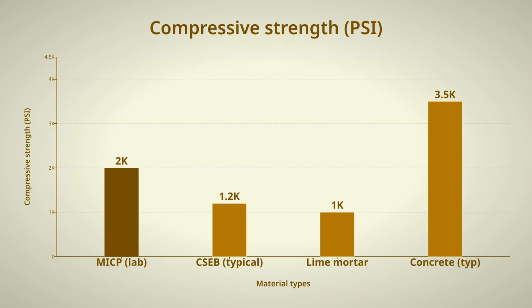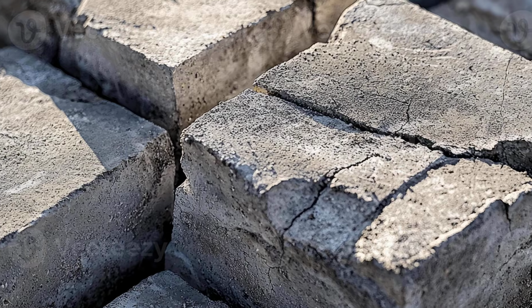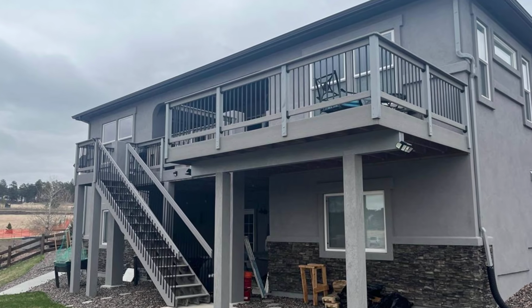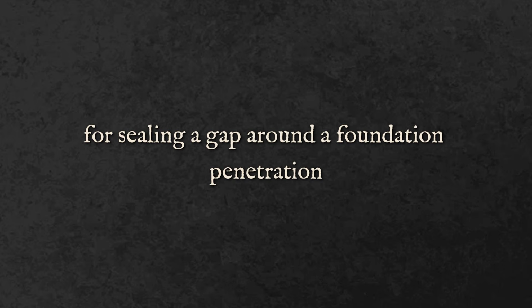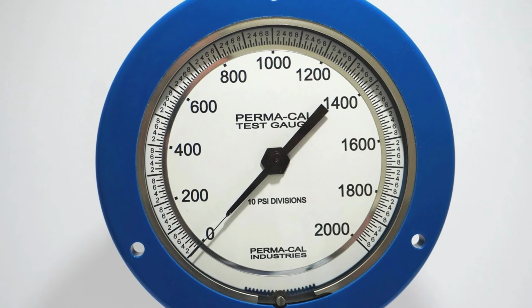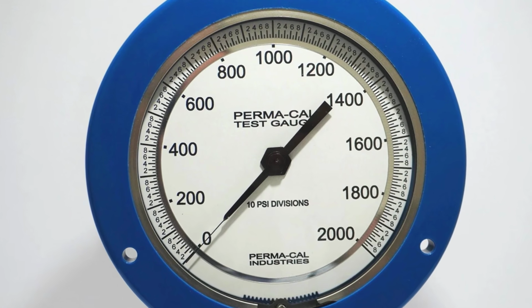Biocemented sand, using the method in that 1923 manual, and refined by researchers at Murdoch University in Western Australia in a series of papers published between 2009 and 2014, tests between 1,400 and 2,600 psi, depending on cycle count and calcium source. That is not structural concrete. I'm not going to lie to you and tell you it is. You are not going to pour a second-story balcony with this, but for a basement crack repair, for a settling step, for a pier pad under a shed, for a garden retaining wall, for sealing a gap around a foundation penetration, 2,000 psi is double what you need and triple what most of those failures require.